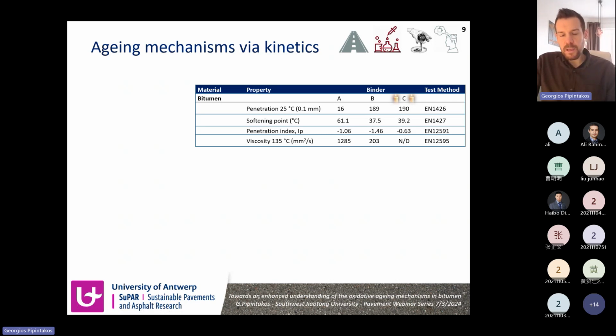So binders A and B are from the same crude, and they vary completely in terms of performance. So the idea here was to choose three binders that have differences between them, to see if we can really support these aging mechanisms, or if they are based, for example, on the performance, on the characteristics of the bitumen. So binders A and B were from the same crude, but they were varying for performance indicators like penetration, as you can see, and other empirical properties.